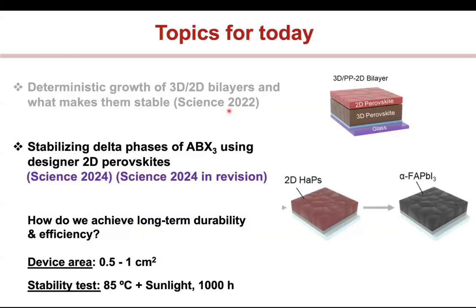Okay, great. So this was very good, right? I showed you a method of combining these two things. But the question that we wanted to answer, as I said earlier, is that what we wanted to get was stability at 85 degrees C. And so I showed you the stability, which was at 60 degrees C. But as soon as we went higher, we found that, in fact, the stability wasn't very good. And so we came up with a new approach of doing this.